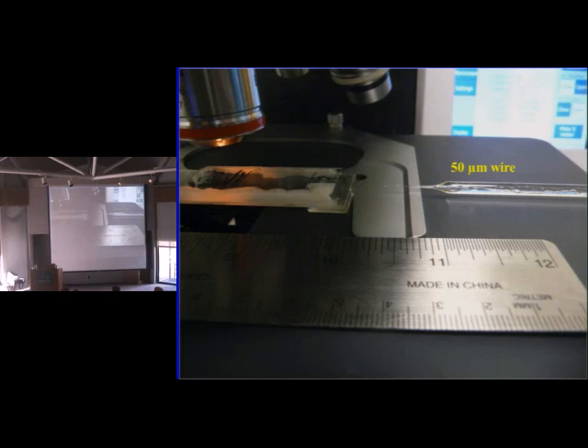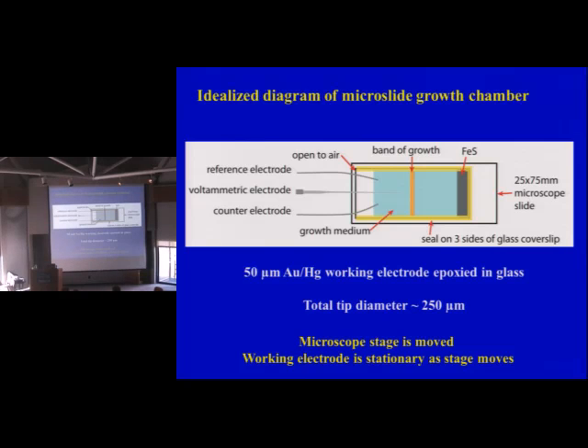In this case, what we're going to do is the following. Here's a nice little cartoon. Here's your FeS in here. You get two slides, one on top of the other. There's maybe 2 millimeter distance separating them. He puts Vaseline and other things around the side so oxygen won't penetrate. We put the reference electrode and the counter electrode on the sides, and the working electrode with a gold amalgam down the center. In this case, what we found was best was actually let the stage move so that the working electrode was stationary and the reference and the counter would actually move. And so actually we found that it was better control using the stage of the microscope rather than using a micromanipulator.